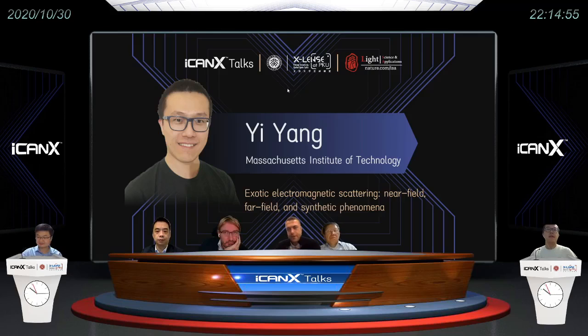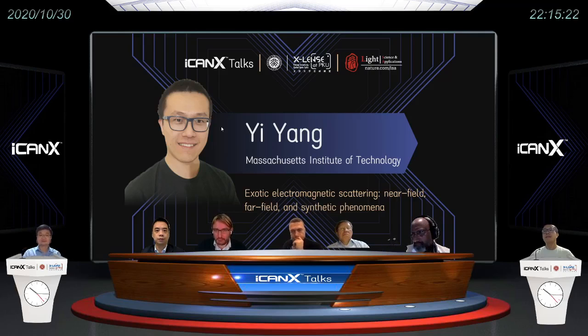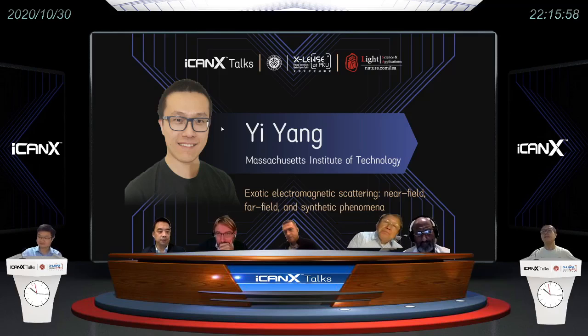Oh, thanks for the question. Indeed, we do model the surface roughness in our structure. And the key to our analysis is that in our fabrication there's a crucial step, which is the atomic layer deposition of aluminum oxide. This process is conformal. So whatever surface roughness is present in the first step is inherited in this layer deposition, and also inherited in later processes. So the surface roughness will be conformal underneath this nanodisk resonator as well as the gold substrate. Our numerical simulation under this conformal condition shows that the surface roughness has a more negligible contribution compared to the change of the gap size given our experimental conditions.